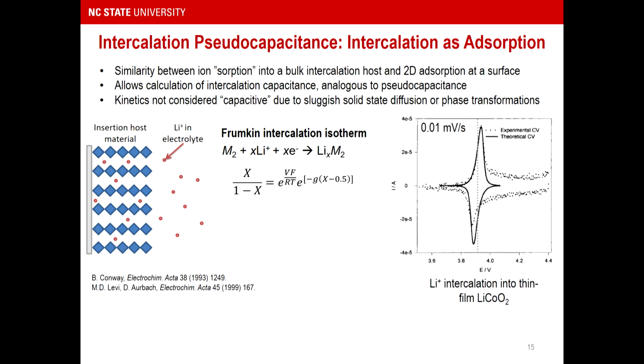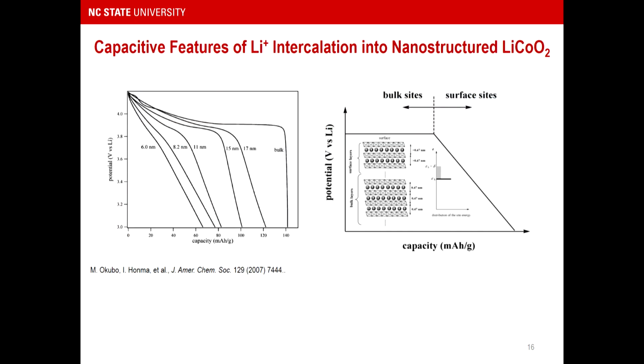And this is an example of lithium intercalation into lithium cobalt oxide at a very slow scan rate. We don't see that mirror image response here. But something interesting happens when you start to nanostructure materials. And this is work that is very beautifully illustrating that. When you begin to nanostructure materials, capacitive features begin to emerge.